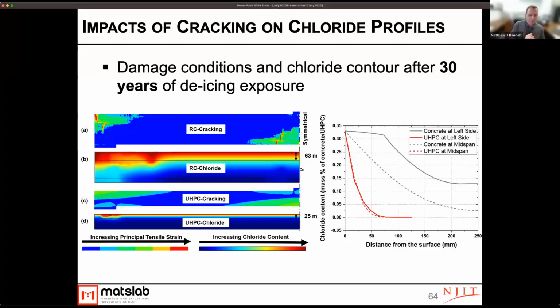And what I'll show you here is just some results of this combined mechanical and environmental conditioning simulation framework. And so after 30 years of de-icing exposure, here are some of the results that we see. So on the left-hand side, what we can look at is two different cracking patterns. The main thing to look at here is that as you move from blue to red in the ones that say cracking, you're getting more principal tensile strains, which is indicative of basically more cracking. And so you see these larger cracks that form in the reinforced concrete near the boundary conditions, as opposed to the UHPC.